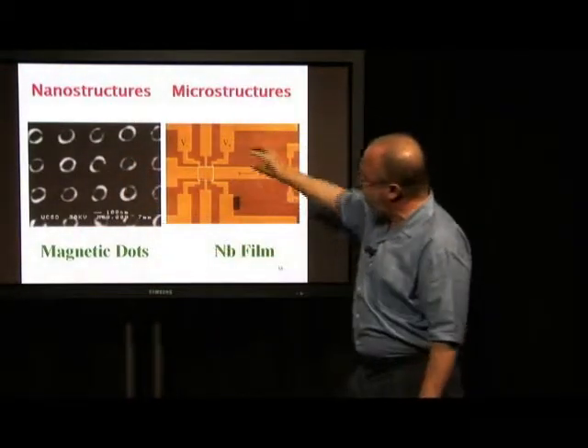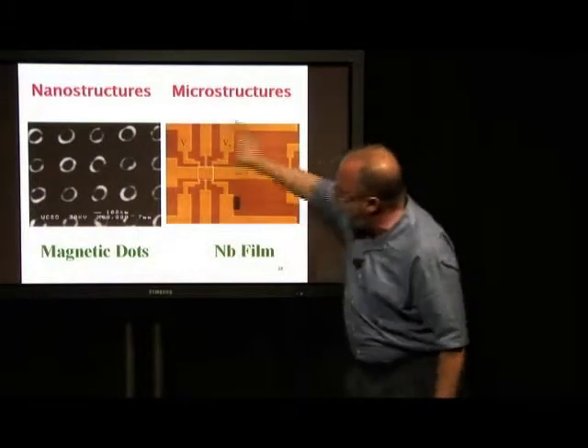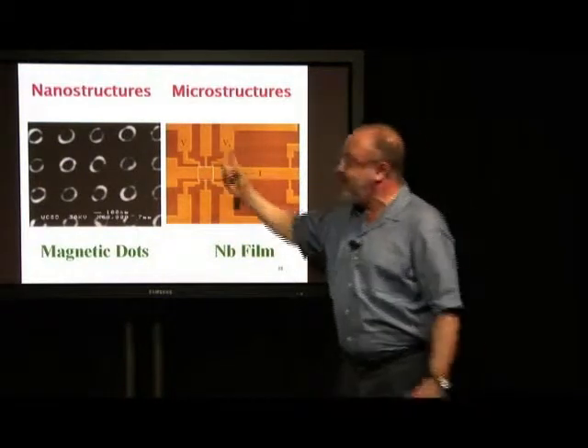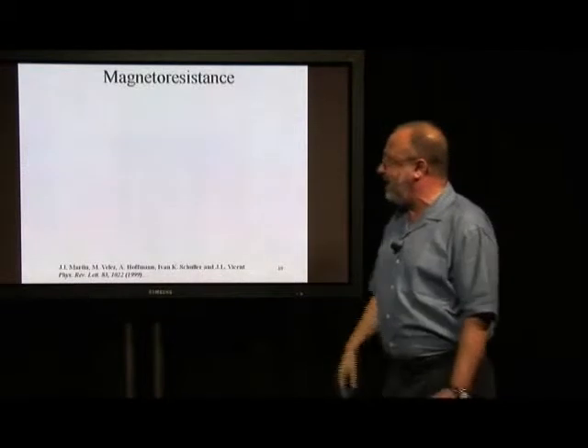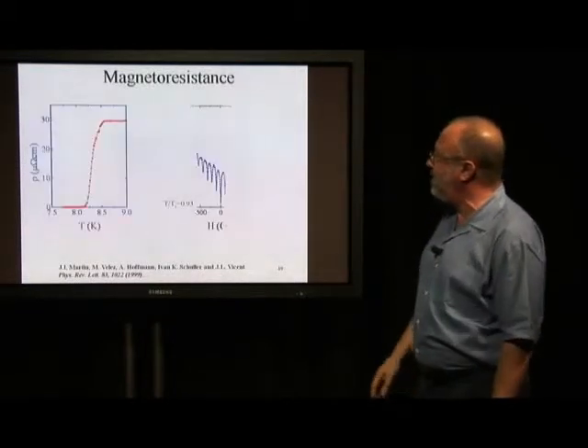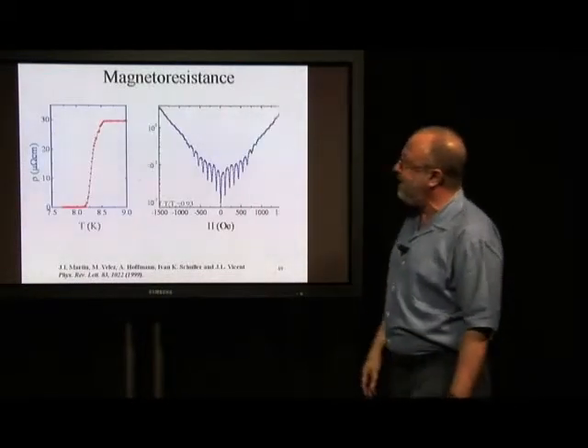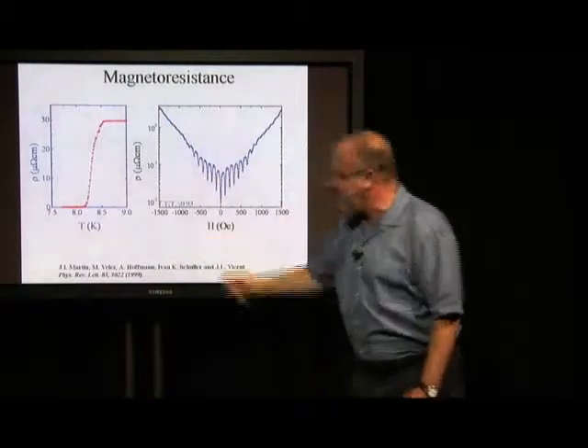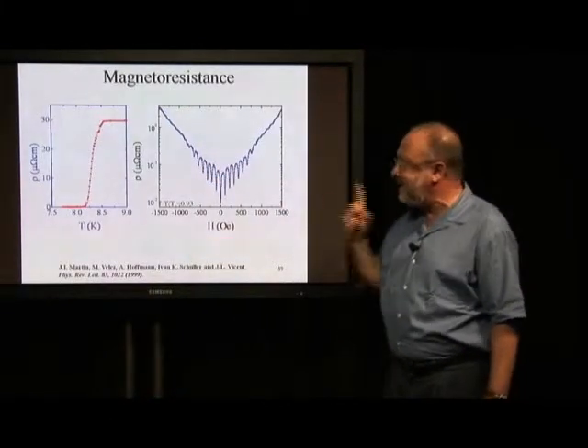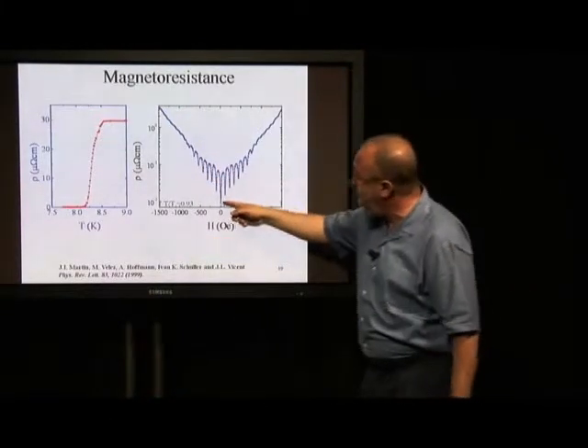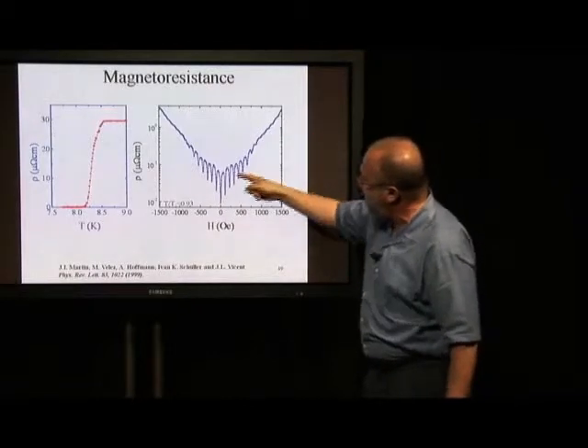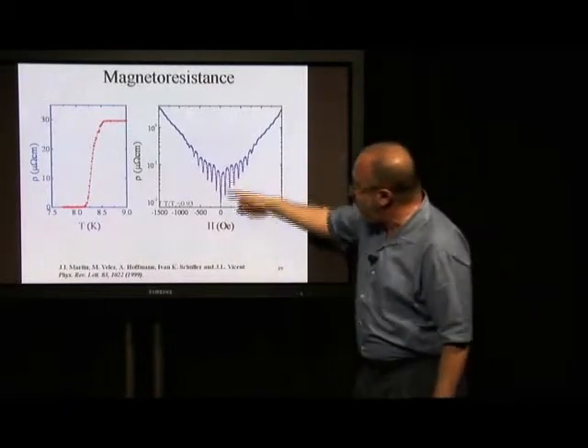And then what you do is you stick them in there, the array, and then you have a niobium film there, and you put a current, and again measure the voltage. And again, I don't have the time to get into the details of this, but one of the interesting things that happens is that the resistance this time, not the magnetization, but the resistance as a function of magnetic field, instead of being a smooth curve, like you would expect, it has all these kinks.